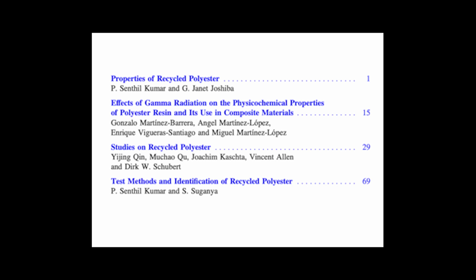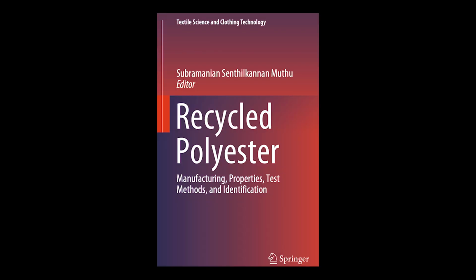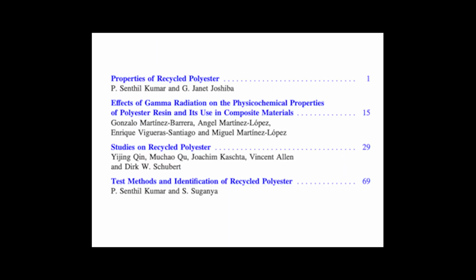Exactly. It really underscores the importance of matching the polymer grade to the process, whether it's virgin or recycled. But contamination clearly still caused problems on the recycled side, even in this controlled study. Oh, definitely. The study carefully tracked molar mass degradation. Remember, that's the measure of how much the polymer chains broke down during melting and spinning. Right, chain scission. And the mixed multicolored flake blend, the rPTA, suffered by far the highest molar mass loss, up to a staggering 30.0% loss in some conditions.